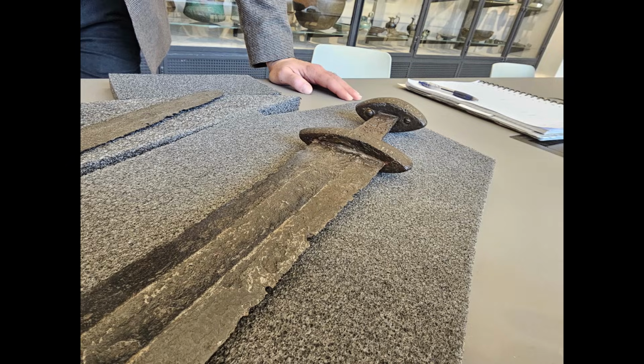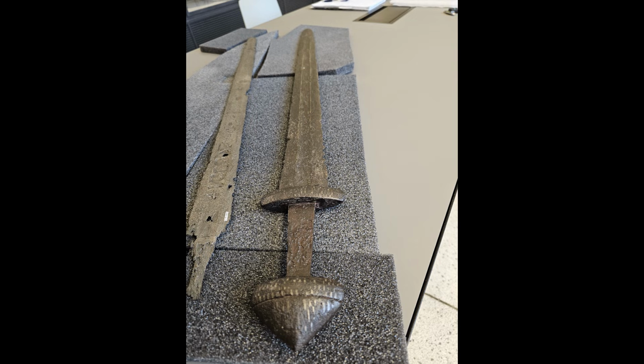indicating that both categories of swords are made from rattlestone iron ore, but that only the Ulfbert swords, which have a cross and a T at the end, are made via a secondary hearth refinement technique. Also, other inscribed swords of the same Viking Age show a very similar chemical composition as the Ulfbert swords and are therefore most likely made from the same type of rattlestone iron ore.